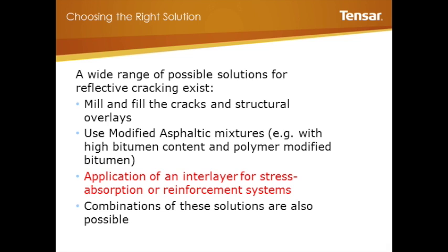Now remember, there are a range of possible solutions for reflective cracking. Some people just use mill and fill. Some people consider modified asphalt mixtures or fiber modified asphalt mixtures. The reality is, if you're using something for reflective cracking, please appreciate you need to see data associated with higher strain related testing as opposed to conventional fracture performance under conventional fatigue fracture. Those are two very different phenomena, so please keep that in consideration before trying those things. And then in terms of interlayer, again, that is for your higher strain levels, and it's better suited for that.